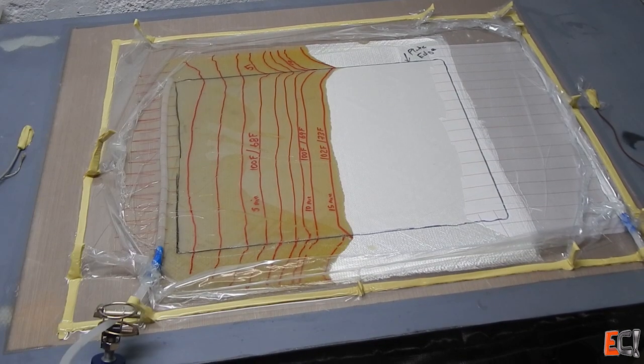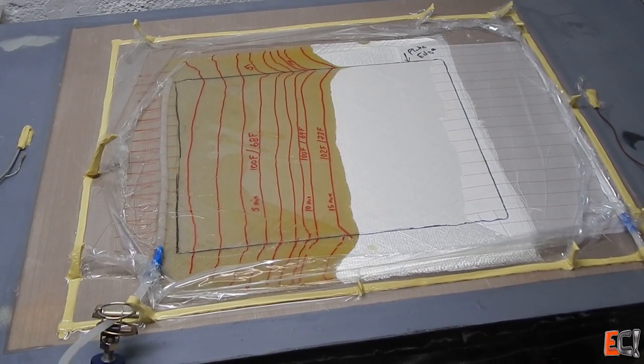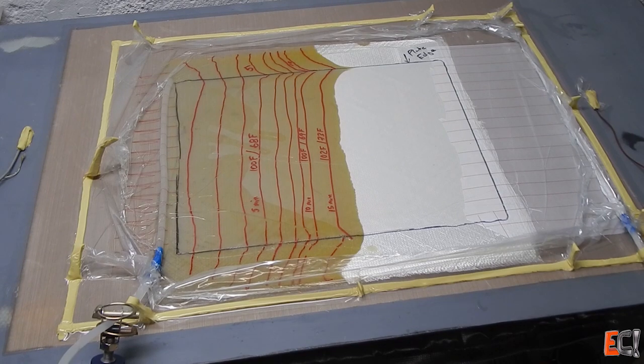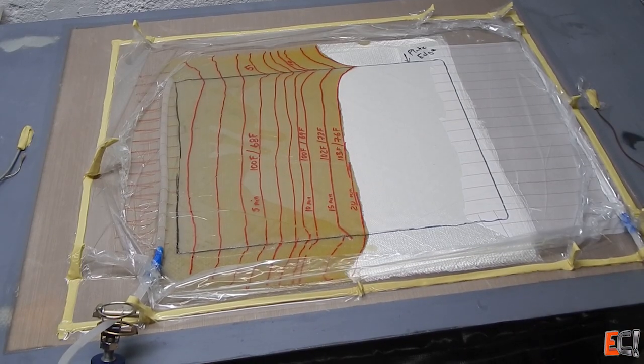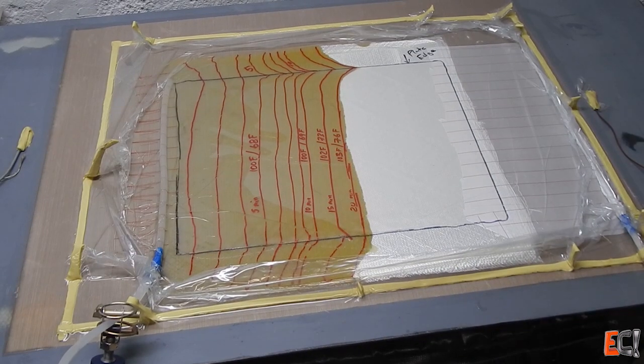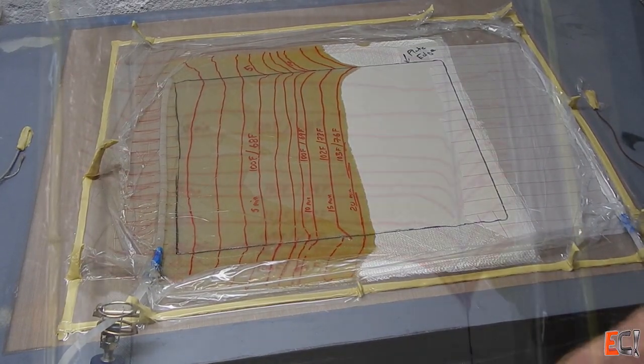I switched to marking every 5 minutes. And right about here, reaching the gel time of the resin. And you can see it turn yellow on the front as it starts to gel. And this is really about it.